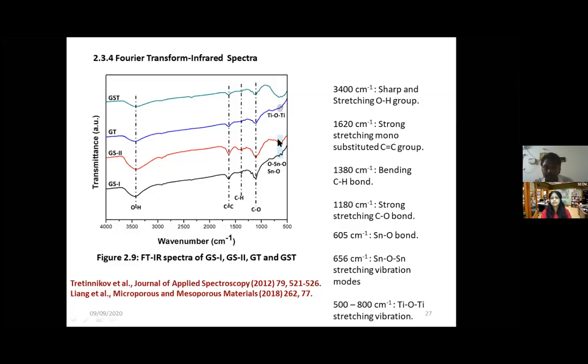And this is the characteristic peak of tin and titanium dioxide. Similarly, here compared to GS1, there is a shift in this tin characteristic peak to a lower frequency. This means that, for example, Sn and O is present, vibrating with stretching and bending vibration at a certain frequency. That frequency has shifted to a lower frequency for GS2. This means the vibrating frequency is lesser. If it is lesser, the van der Waals force will be lesser compared to GS1 here. So this tells us the first point: from the precursor, how the original nanomaterial is being formed.